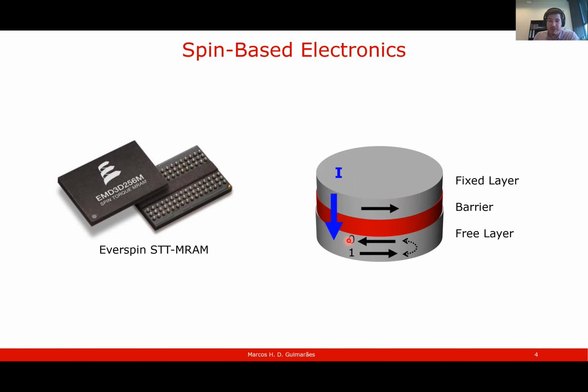But if we drive a high current through this barrier, through this stack, then we can switch between 0 and 1, so between parallel and anti-parallel, and this is how we write the bit. And if we drive a smaller current, that's how we read the bit. But the problem is that these barriers are very, very fragile, and they break very easily. So we only have a few times of read and write before the memory cell degrades.